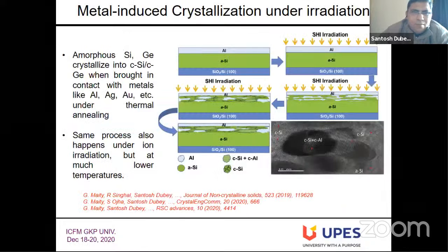Metal-induced crystallization means, suppose we have amorphous semiconductor materials like germanium and silicon. You can make crystalline germanium or crystalline silicon under irradiation followed by annealing, if you irradiate that along with some metal like aluminum, silver, and gold.